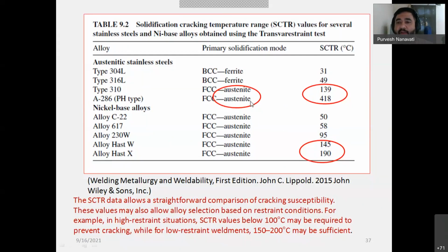Once again, I'm repeating, when your primary solidification mode is austenite, for any austenitic or nickel-based alloy, right? Most of the time, austenite, you say 304, 316, 310, A-286, there's a precipitation grade, the nickel-based alloys C-22 to 617, alloy X, and all this. If your primary mode of solidification is austenite and they have a high solidification temperature range, that is SCTR, then your crack is certain, right? So you have to do something to avoid the crack, right?